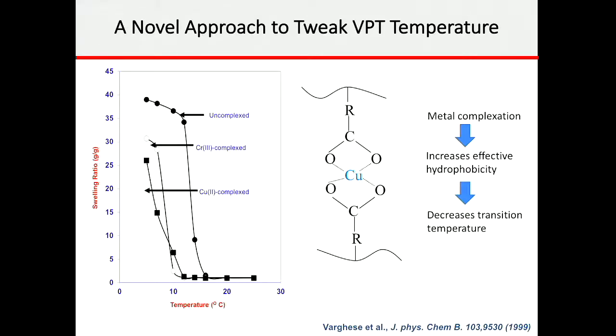For example, if you see the uncomplexed part of it, and then complexation, how it changes, it is obvious that the metal complexation actually will increase the effective hydrophobicity because it will lock in the carboxyls, so as to say, making it hydrophobic, and that will decrease the transition temperature. So there is one more handle. So what am I talking about? I'm talking about controlling hydrophobicity or effective hydrophobicity by changing the methylene groups, putting in metal ions, and so on and so forth. So there are different handles that you start having.